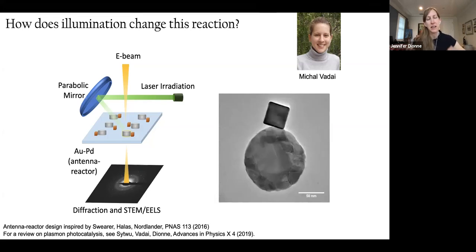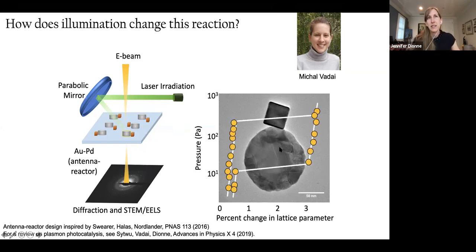And when we're looking at light, we wanted to start off with our palladium nanoparticles, which are not particularly good light absorbers. So what we did is couple those palladium nanoparticles to a gold nano antenna. This is an antenna reactor design inspired by the Halas and Nordlander labs, and in particular by then a graduate student, now my postdoctoral researcher, Dayne Swearer, who first investigated how you can couple an optically active material like gold with a catalytically active material like palladium to enable more efficient catalysis. So we have a gold disc that we fabricated by electron beam lithography, and then we sprinkle on the palladium nanoparticles, the catalyst.